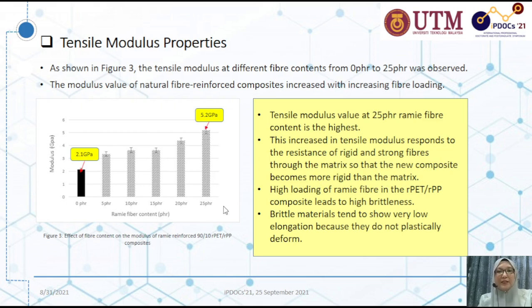This increase in tensile modulus responds to the resistance of rigid and strong fibers through the matrix, so that the new composite becomes more rigid than the matrix. High loading of Rami fiber in recycled PET, recycled PP composite leads to high brittleness. Brittle materials tend to show very low elongation because they do not plastically deform.